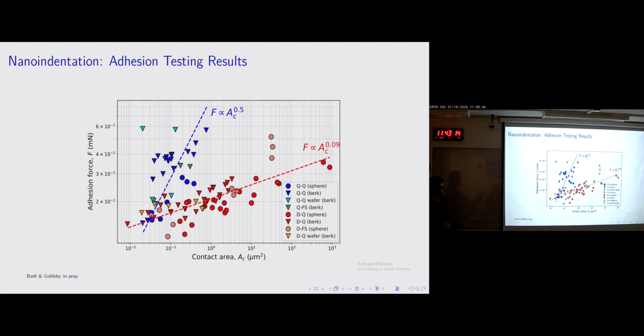I get two trends. The red group is our chemically inert diamond on quartz or diamond on silica, and the blue group is quartz on quartz or quartz on silica. And this is experimental data. It's quite messy. I'm not saying these experiments are clean. I've done them as clean as possible in terms of chemistry and contamination, but it's a very subtle signal. What you can see here is that they follow very different trends.